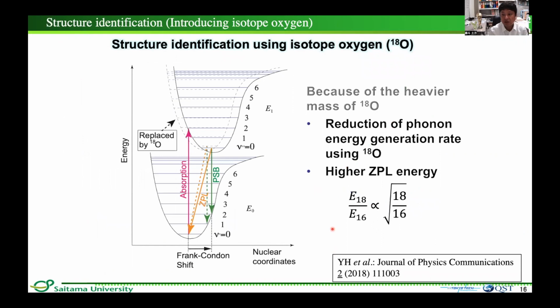Firstly, we investigated the presence of oxygen using isotope oxygen. Because 18 oxygen has a heavier mass, fewer phonons should be generated when inducing optical transition. In addition, the zero phonon line energy of 18 oxygen should have higher energy according to this basic spring mass theory.